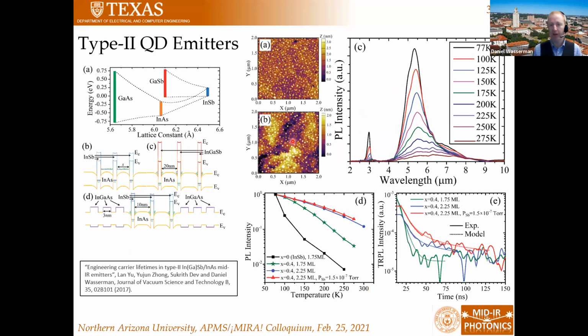So we demonstrated that you could actually, because the lattice mismatch in this case between indium gallium antimonide and indium arsenide is basically the same as the lattice mismatch between indium arsenide and gallium arsenide, which gives you quantum dots, that you can actually form these type 2 quantum dots on indium arsenide substrates. And so we showed that you could get this nice quantum dot formation, and you could get very nice mid-infrared emission. And actually the mid-IR emission is pretty temperature stable. I mean, you lose about a factor of 4 when you go from low temperature to room temperature, but all things considered, for a semiconductor emitter in the mid-IR, that's really not so bad, right?